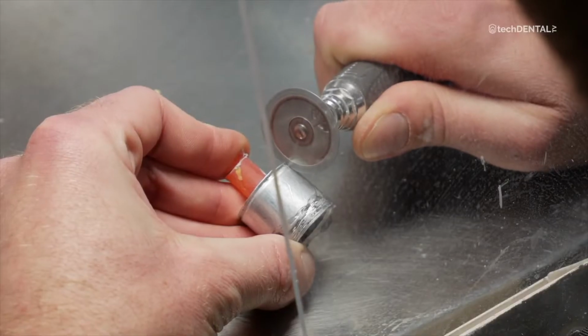You put in a new cartridge, the same, the next the same, then, most often nervous, you just start looking for the cause. Meanwhile, there is a simple method that allows you to clearly assess whether the failed injection was the result of failure to melt. It is enough to cut open the cartridge and see the structure of the molten material. If you can see clear plastic granules separated by gaps, the material is unmelted. If the surface of the material in the cartridge is smooth, the melting process was right. The cause of the failure must be looked for elsewhere.